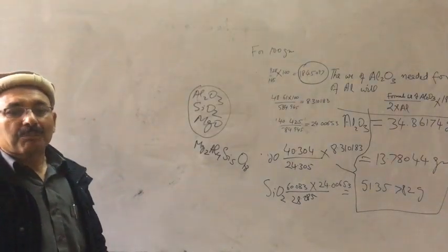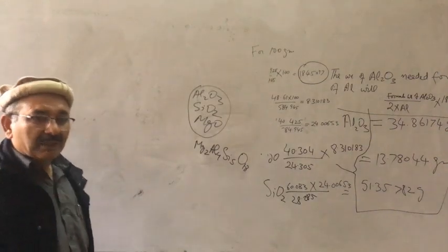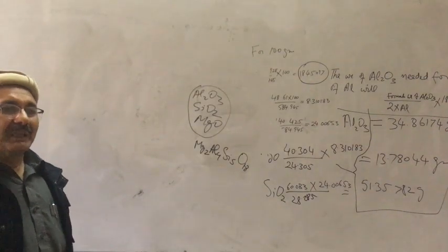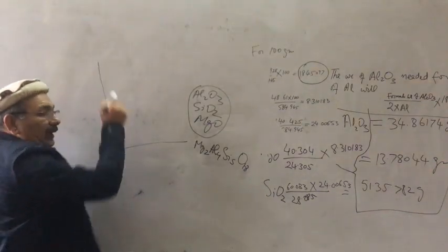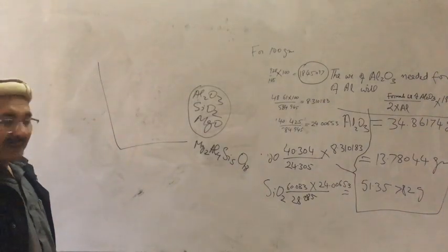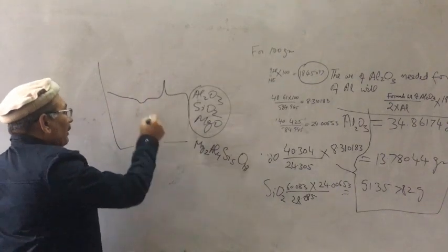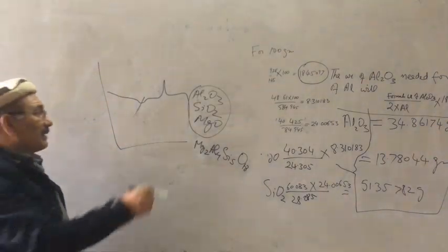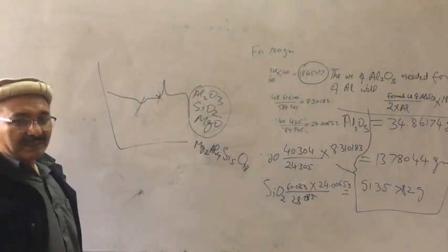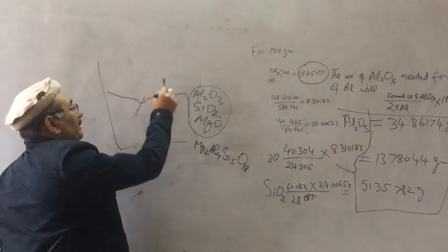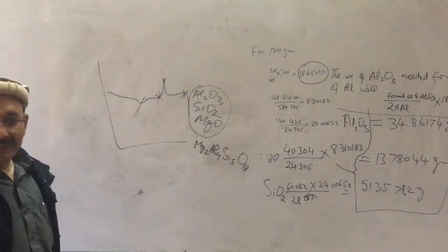...but in the powder form. And for that purpose, how do you know that the powder will react at that particular temperature? You do DTA of the sample or DSC of the sample. The DTA or DSC, for example, tells you about the glass transition temperature, the start of crystallization, the peak crystallization temperature, and the melting temperature of the material.